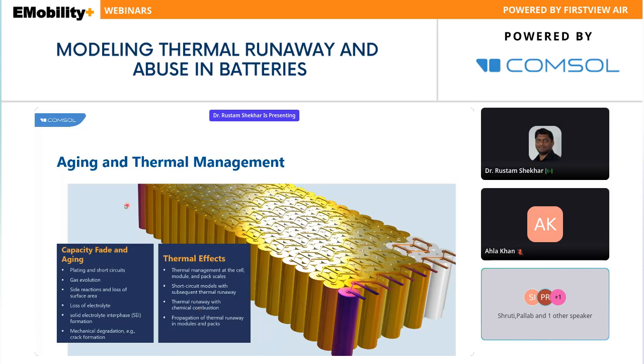So if you want to account for the failure mechanisms, aging is one factor which will lead to the failure of the battery, which includes plating, short circuiting, gas evolution, side reactions due to the surface area, loss of electrolyte, SEI formation, and mechanical degradation, which means particle cracking or crack formation. So all these failure mechanisms which are listed here can be incorporated, and if you know any other kind of mechanisms as well, those also can be incorporated, and then make a detailed electrochemical model.